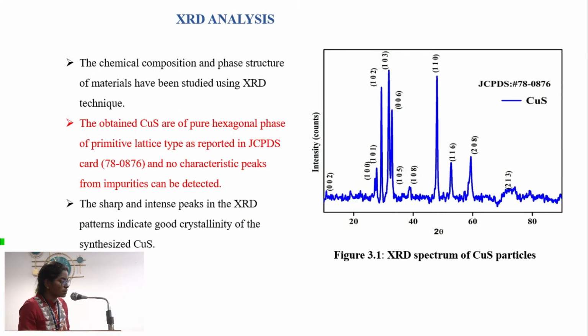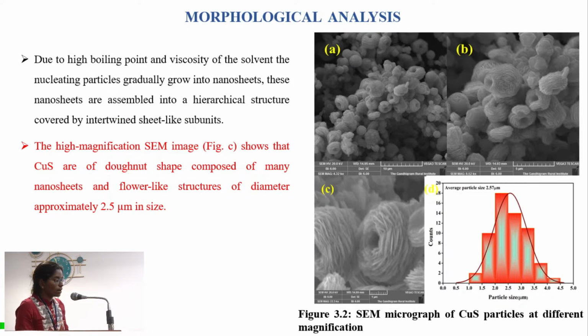In XRD analysis, I have obtained the hexagonal phase of copper sulfide. The pure form of copper sulfide is confirmed through the JCPDS card number 78-0876. Through the sharp peaks we can confirm the highly crystalline nature of the obtained sample. Through the card we have confirmed the hexagonal phase of the sample, and through morphological analysis I have confirmed the flower-shaped morphology. This morphology is attained through the viscosity of the solvent. Mainly the viscosity of the solvent controlled the nucleation of the particles and arranged the material into sheet-like subunits, allowing them to form a flower-like morphology.